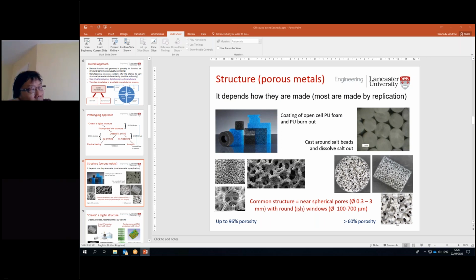But, and people have already been talking about this, we can end up generating structures which themselves have some porosity. And one of the figures at least shows a very textured surface on that porous structure. And on the right-hand side, an alternative route is we cast a metal within the holes that separate things like salt beads. And we dissolve or flush out the salt in warm water, and we create structures where the walls are very, very solid. So we've already talked a little bit today about how we need to really match the things that we build to the structures that we might be wanting to use in our parts, and I'll come on to that a little bit later.